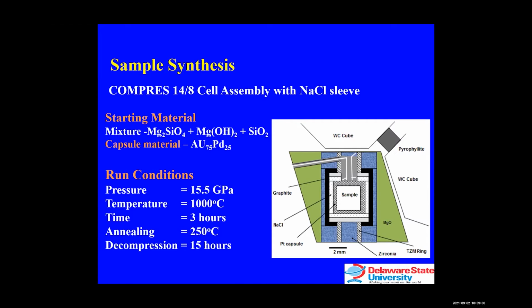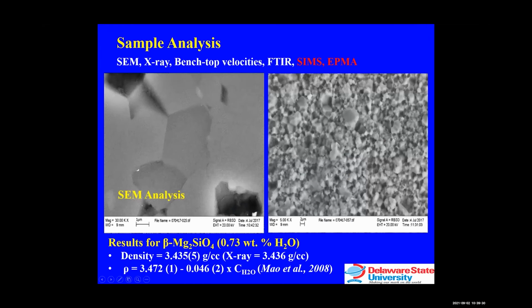The PT conditions are shown here. The PT condition is 15.5 GPa and 1000 degrees. The only thing that we vary is the annealing time, which depends on the water content of the sample. This is actually in contrast to the dry sample. It takes only 1 hour and the sample is completely annealed and good. So we do extensive characterization on test specimens to optimize the conditions for fabricating suitable samples for ultrasonic experiments. There are very stringent requirements for the sample in order to be suitable for ultrasonic measurements.